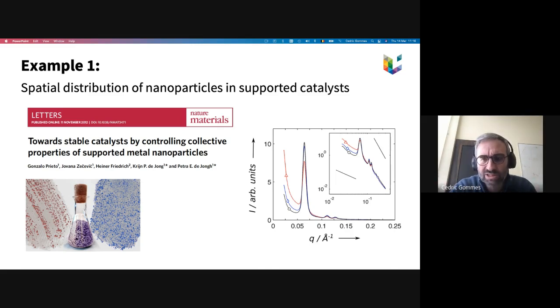And this spatial distribution had really important influence on the stability of these catalysts. But when you do microscopy, you're always characterizing an extremely small fraction of your sample. This thing here would be like 100 nanometers. And if you estimate the weight of an object like this, it is a femtogram, so 10 to the minus 15 grams. And you have to compare that with typically the ton, because that's the scale at which these materials are used in chemical processes. So the ratio is 10 to the 21.